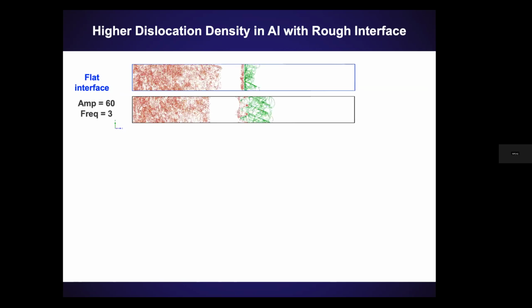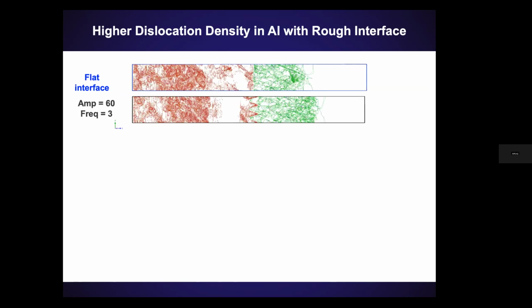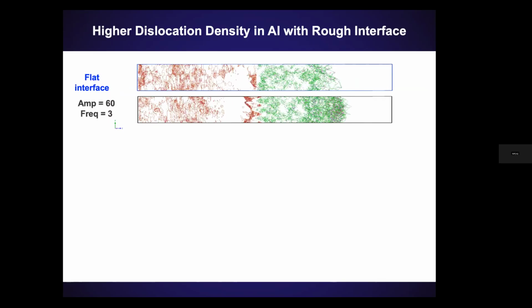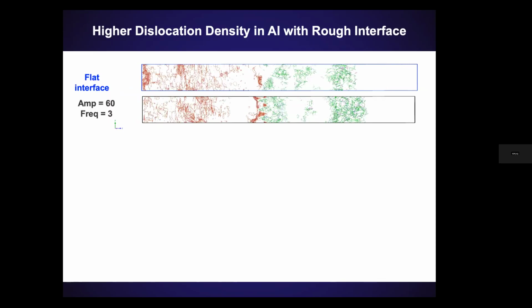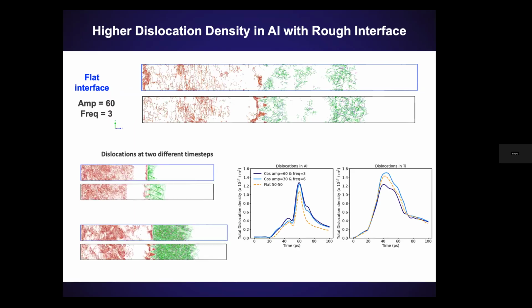In fact, when you look at the dislocation nucleation, similar to what we saw under uniaxial stress loading, you see a lot more dislocations nucleate from the rough interface as compared to the flat interface. And while they mattered under uniaxial stress loading, because you had a different elastic to plastic transition stress, under uniaxial strain loading it doesn't matter. That impedance mismatch is ruling the day because you're failing in aluminum no matter what.